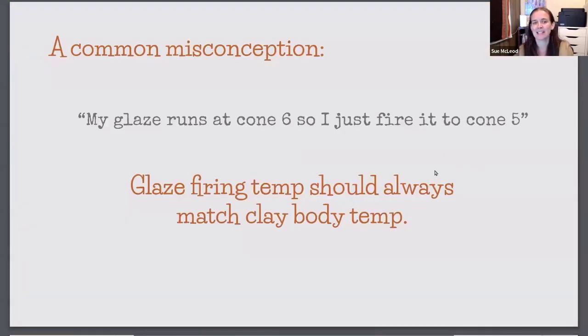So a common misconception is, my glaze runs at cone 6, so I just fire it to cone 5. Now, the reason why this is not really a good strategy is that your glaze firing temperature should always be based on the maturing temperature of your clay body. So you don't want to underfire your clay body, which means it won't be vitrified.